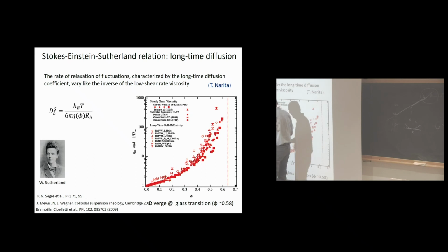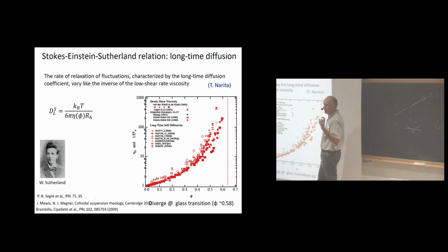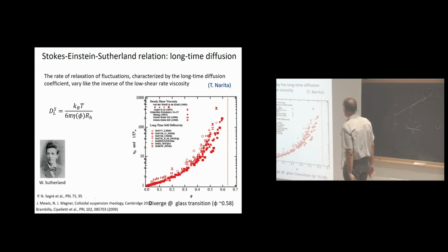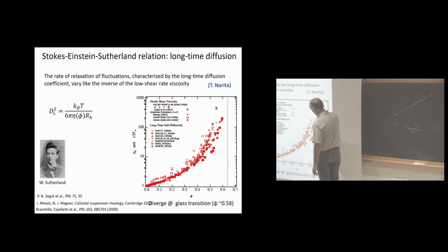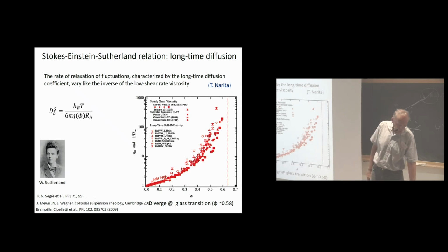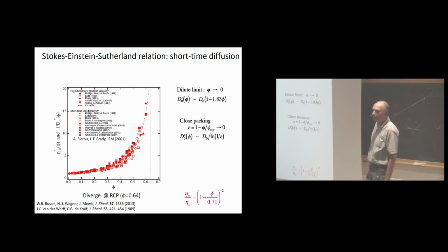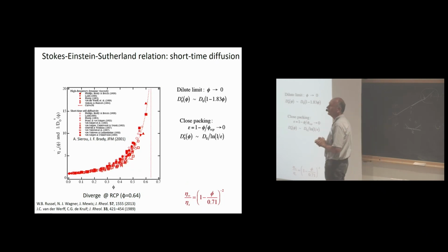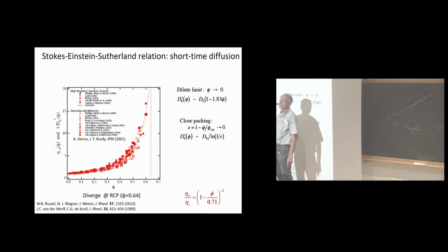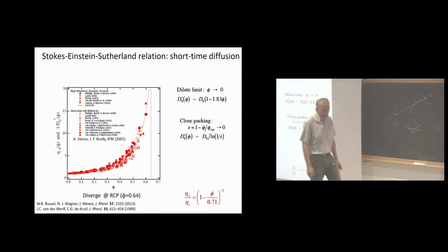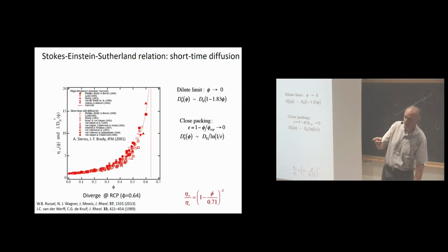We'll go fast now. This data is viscosity and inverse diffusion. This is shear viscosity, so there will be long-time diffusion, and the divergence along with simulation data, with scattering, of course, occurs at glass transition. Now, if you do the same thing with the high-frequency viscosity and the short-time diffusion, you have the same behavior, but the divergence will occur at the maximum close packing. That will be the difference, really. Okay. And I need to speed up and address your question.